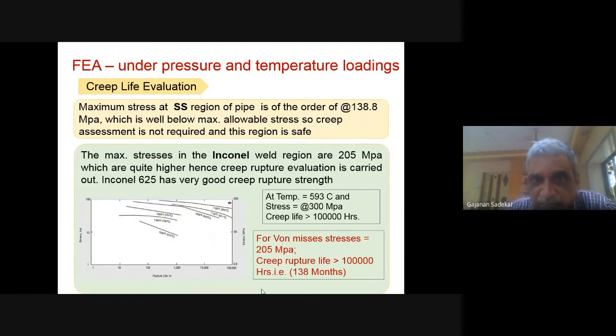The maximum stress in the SS region of the pipe is of the order of 138.8, which is well below the maximum allowable stress. So creep assessment is not required, and this region is safe. The maximum stress in the Inconel weld region is 205, which is quite a bit higher. Hence, creep rupture evaluation is carried out. Inconel has very good creep rupture. We found the creep life is more than 100,000 hours at 593 degrees centigrade, which is about 138 months. So Inconel alone has no problem. Stainless steel alone has no problem.